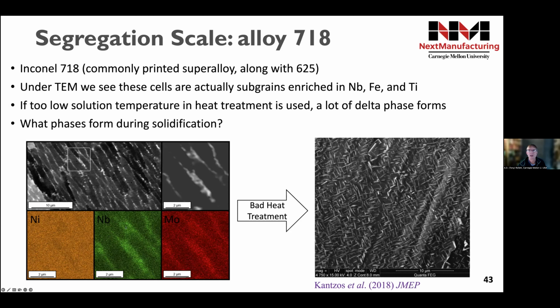And so what it's telling you is that niobium in particular is heavily segregating to the interdendritic space. That's at first blush a surprise because of that very high cooling rate, 10 to the 6 per second. But it turns out that microsegregation can only be suppressed in a few circumstances, and definitely not in this material.